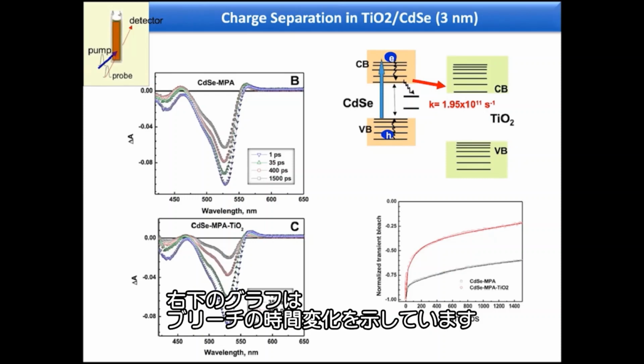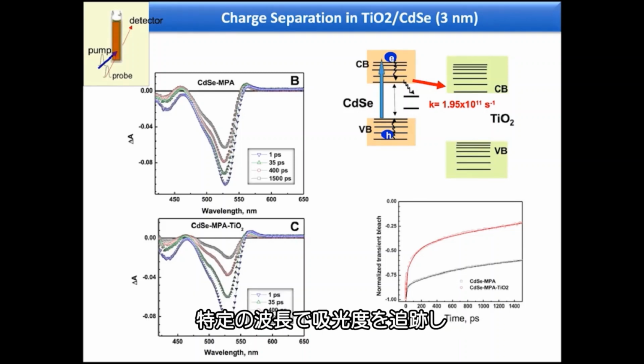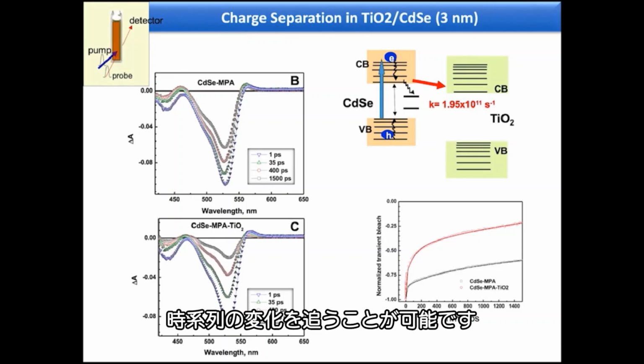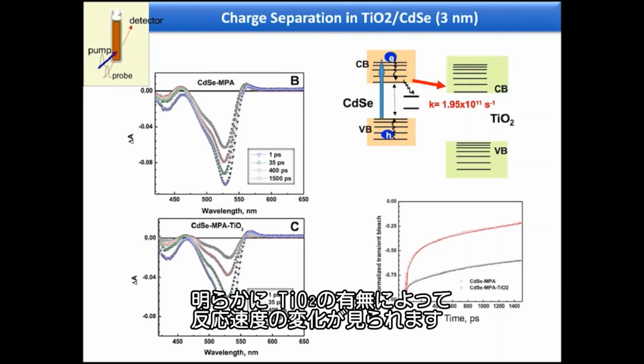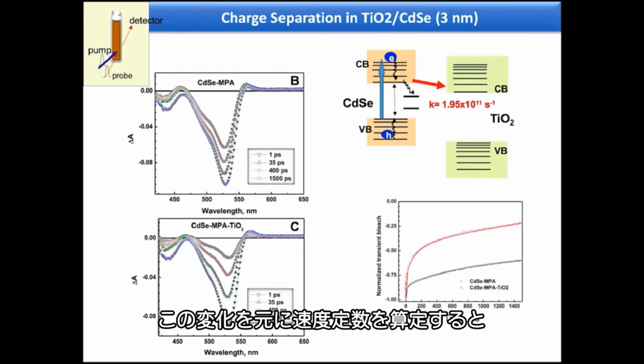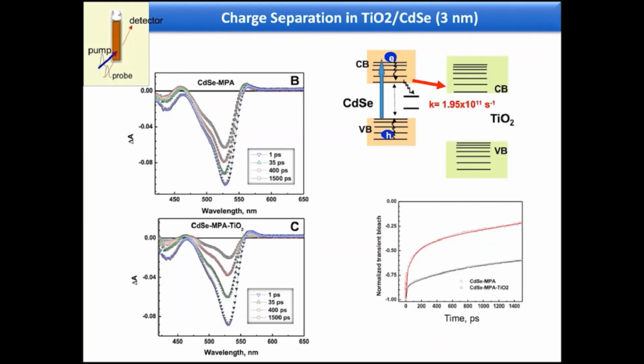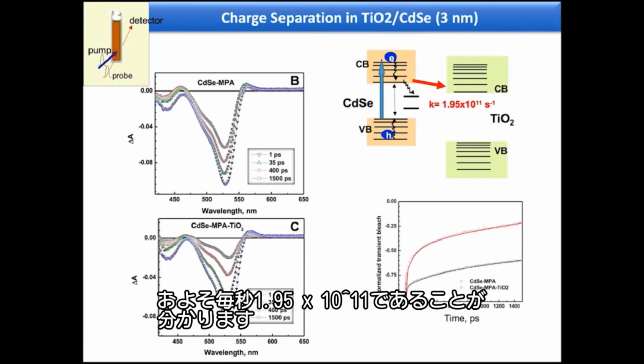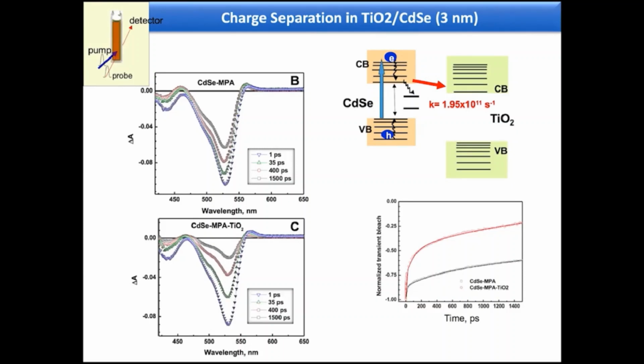In the bottom right panel, you will see there is a bleaching recovery trace. That is, you monitor the absorbance at one fixed wavelength and then see how it changes with time. And clearly, with and without TiO2, there is a difference in the kinetics, and based on this difference we can calculate the rate constants to be of the order of close to 1.95 times 10 to the 11 inverse seconds.